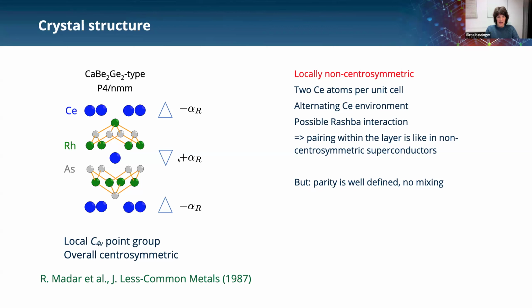So if you imagine that you have a superconducting pairing dominantly in this layer, then this pairing would be like in non-centrosymmetric superconductors, where you can have effects like singlet and triplet mixing, for example. However, in this material, parity is well defined because it is overall a centrosymmetric structure. You can see that by knowing that the inversion center is here in the middle of the line connecting the two cerium atoms. Okay.